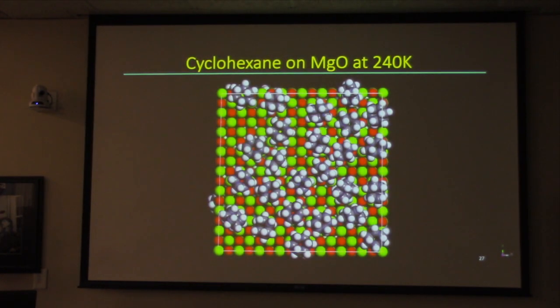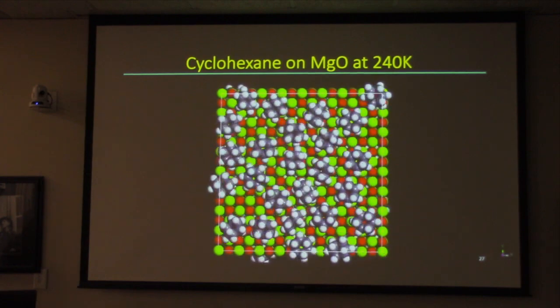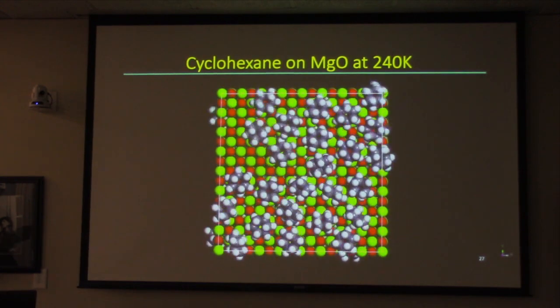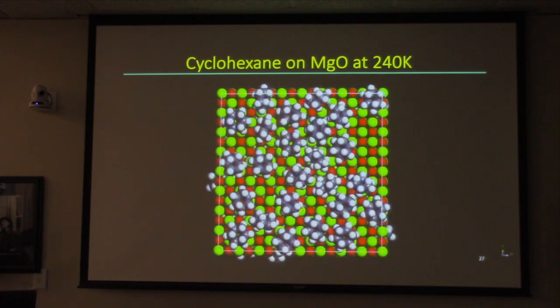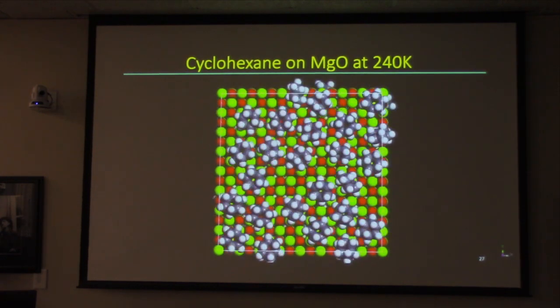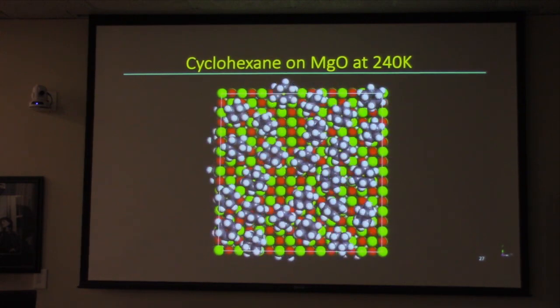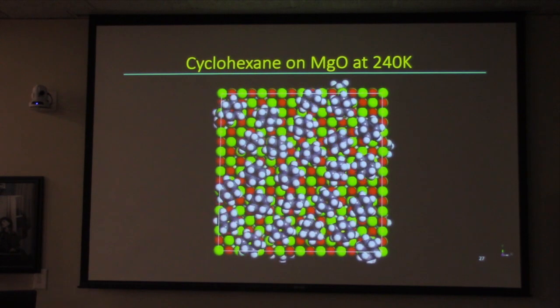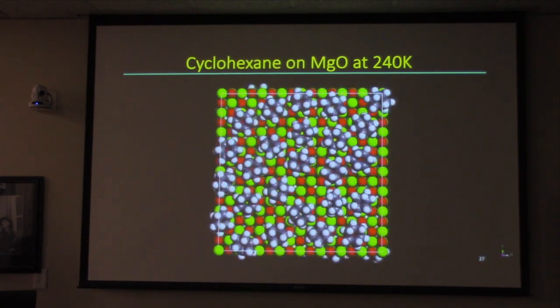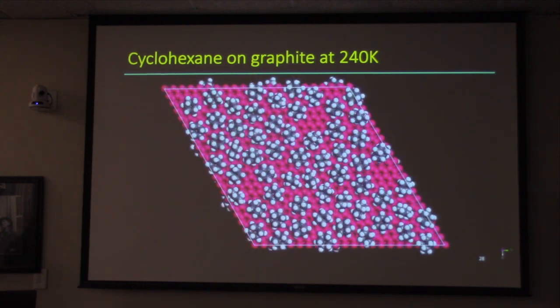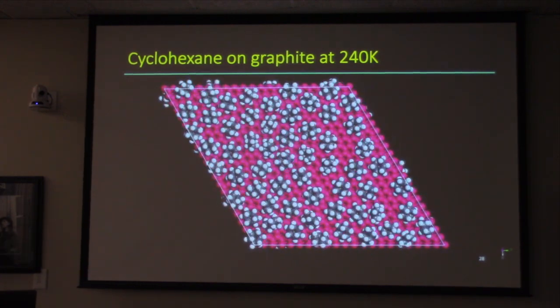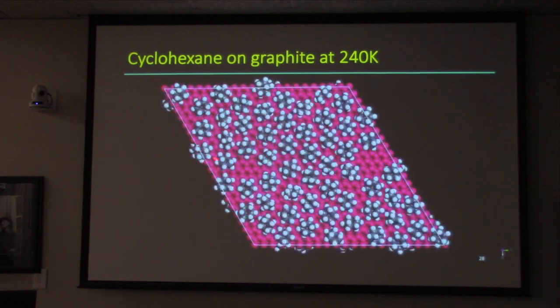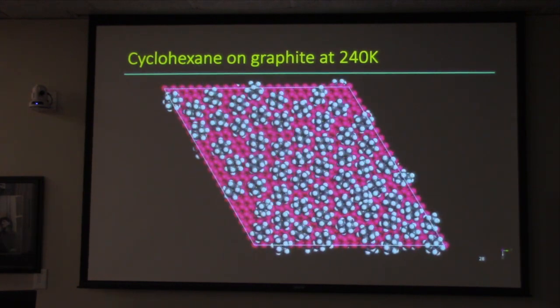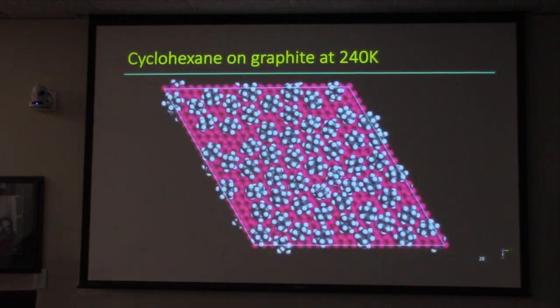So you can do these things, and I just said that it stabilizes this layer close to the surface. Well, what do these simulations look like? Cyclohexane on MgO is kind of cool because, remember, the surface has fourfold symmetry, so the molecule kind of runs along like a wobbly tire. And if you watch it, the surface kind of wags and jiggles. If you put it on graphite, it hops over to another top of the hexagon, spends some time there, and then rapidly moves to another one. So there are very different dynamics, and that's one of the things we study with neutrons. If you look really carefully, and you can look at it later if you care, the molecules spend a lot of time spinning around over the hollow sites of the hexagons, and the dynamics are very different.